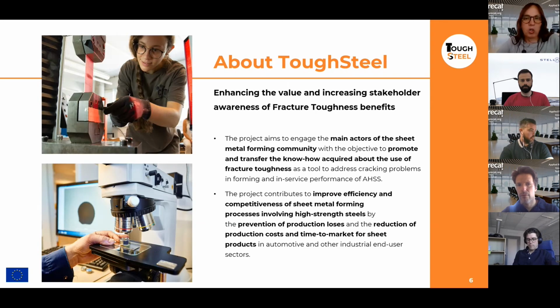That's why the ToughSteel project aims to disseminate to the main actors of the sheet metal forming community the possibility of measuring the fracture toughness by the use of the methodologies that have been developed in previous projects, the possibility of measuring the fracture toughness in thin sheets, and using this fracture toughness to effectively address and solve crack-related phenomena such as edge cracking, for example, and also to select and develop advanced high-strength materials with optimized crash performance. The project will contribute to improving the efficiency and the competitiveness of the sheet metal forming processes involving high-strength steels.